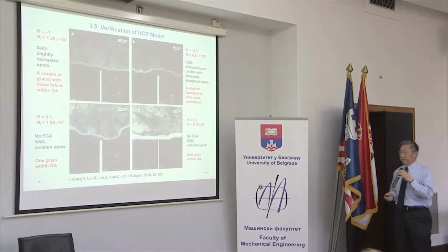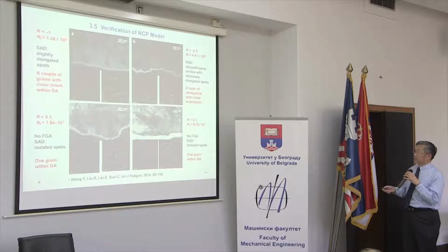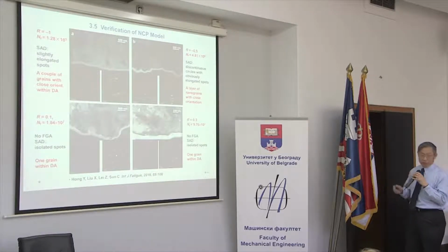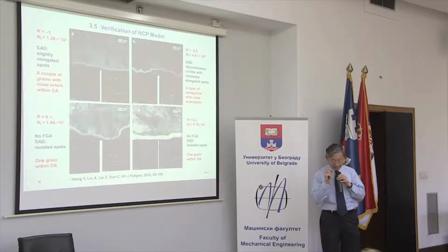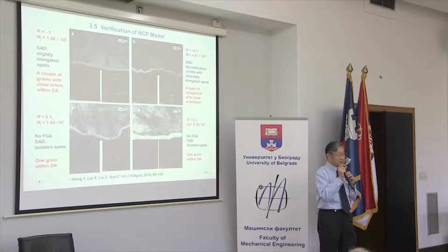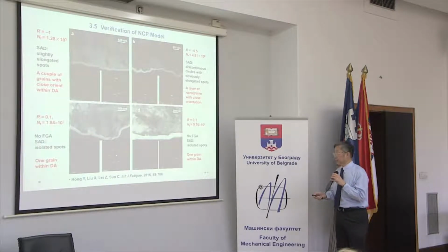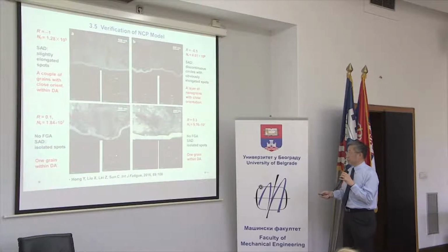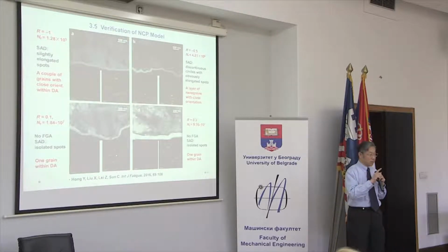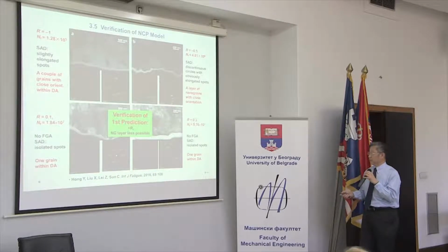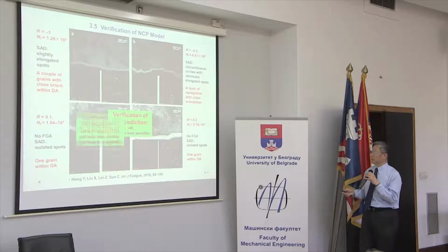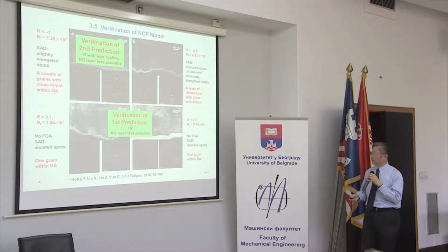And then we performed some further experiments. And this one is just 25 cycles. It's somehow insufficient. And we may see that the diffraction is a type of extended diffraction spot, meaning it's a kind of texture phenomenon, not very much refined microstructure. And for this one and this one, there are 0.1 and 0.3 stress ratio. And the diffraction underneath the fracture surface shows all isolated spots, meaning no evidence of microstructure refinement. So this is the verification of the first prediction, and this is the verification of the second prediction.